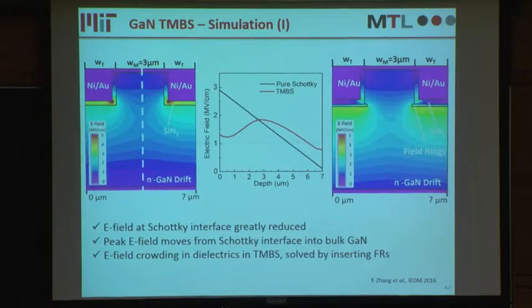We also implanted some field rings into the trench bottom, and this can move the peak electric field from the trench bottom deeply into the bulk gallium nitride. So that's the concept for the design.